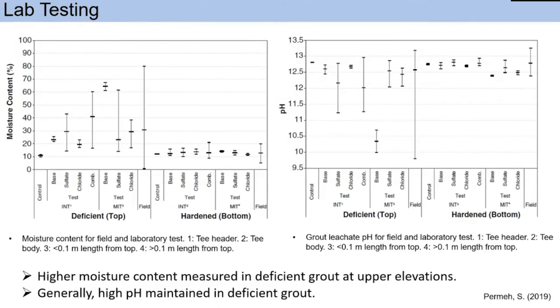MIT can facilitate grout deficiency, shown by differentiation in moisture from upper and lower elevation. These MIT samples were cast using excess amount of water as shown in the last slide. These are the results from moisture content and the pH. Here we can see normally higher pH maintained in deficient grout. This is deficient and this is hardened grout. And moisture content is also much higher in deficient grout. This is hardened grout.